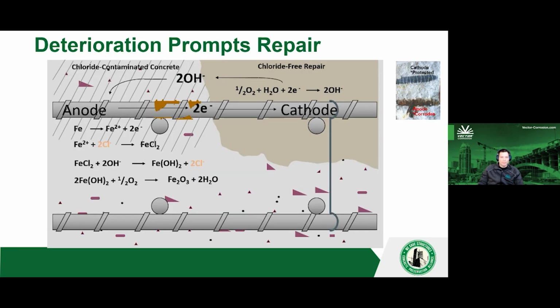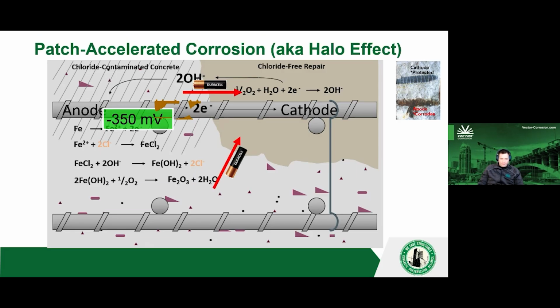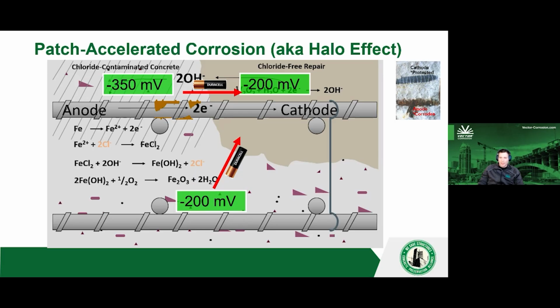So in this case, with just a regular patch repair, right here, you've chipped back until you found sound concrete, you cleaned up the bar as best you could, but you can see what's left. Chloride contaminated concrete immediately adjacent to your repair. So the unintended consequence from repairing this damaged concrete without understanding or addressing the underlying corrosion is patch accelerated corrosion. All that happens is the corrosion activity flips to the area adjacent to your repair. You get corrosion and you get cracking and spalling.